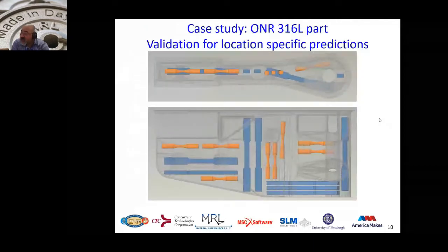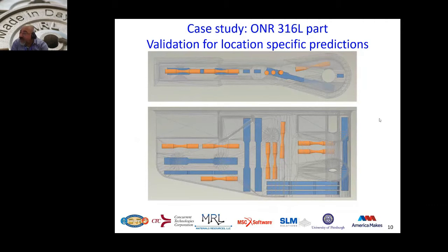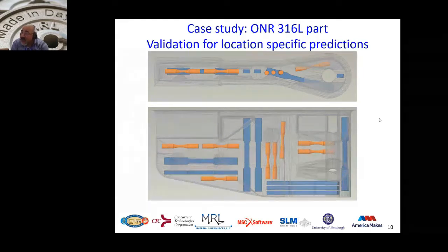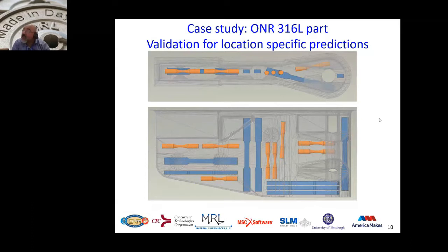The test plan that you see on slide number 10 is showing the locations that we chose as a team to pull fatigue samples as well as tensile samples. And for every one of those locations, we had predictions of the fatigue life, as well as the tensile behavior of the material, as well as microstructure. Then Mike Timms from CTC later on took this data and compared it with the experimental measurements through a blind test that was shown to the Navy later on. Going through the whole slides again, we're going to quickly take you through the process.